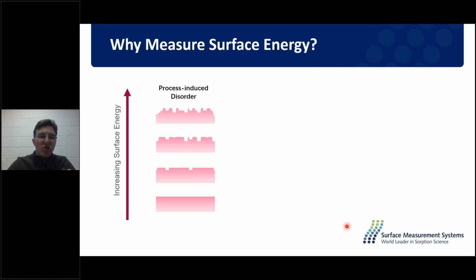Here on this slide, we can now see a number of different surface scenarios. So we have a very rough surface here that we can see at the top. And this is a scenario that we would see higher surface energy. You can imagine we've got lots of atoms or molecules at the surface of this sample, which are covalently not pleased, which have these dangling bonds, which are non-covalently satisfied. And it is these dangling bonds that are giving it that higher surface energy. You have some very unsatisfied parts of this surface compared to some very satisfied low energy parts of this surface. So we would say this surface, this higher roughness, is giving it that higher surface energy.